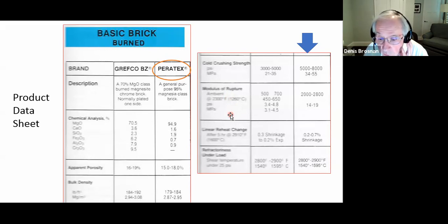Just interpret it as meaning typical. There's a reheat change value for the refractory at a particular temperature. This is a way of characterizing most refractories because you don't want them to shrink in a furnace lining at the use temperature significantly. Otherwise, brick joints will open up and other bad things will happen. And there is some refractoriness test, refractoriness under load in this case. So most of our products that we have will have a product data sheet, and most of the raw materials that we have will have a product data sheet as well.